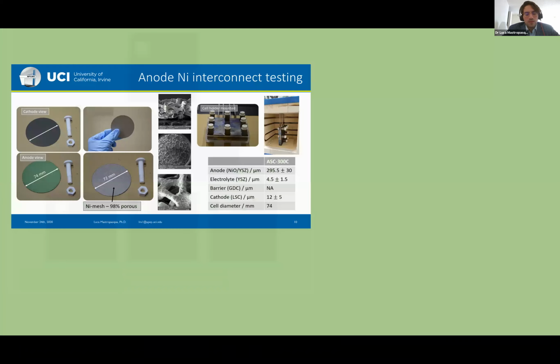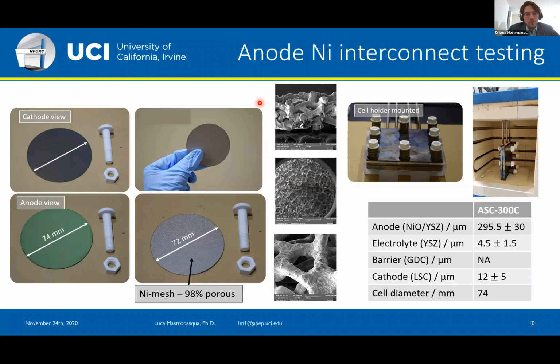So these are some of the pictures of the fuel cell that we are testing. This is the view of the fuel cell on the cathode and anode side, and this is the current collector that we are testing. It's a nickel mesh, really porous, 98%, and you can see the pore sizes here. And again, we have this setup where we mainly test the solid oxide cells with and without these new current collectors. These are contracts from companies that are interested in developing, especially, the microstructure morphology of these materials.